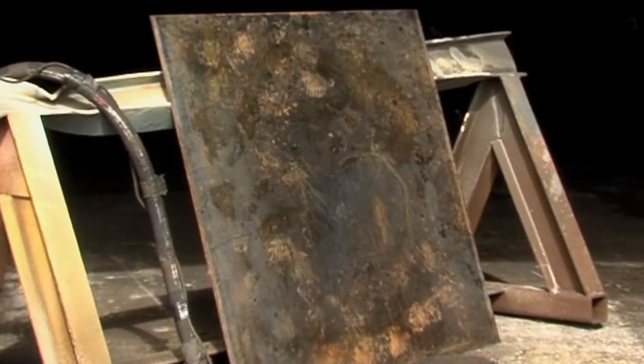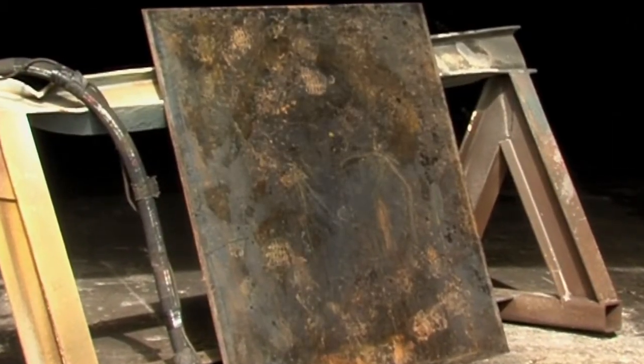The view under the microscope tells a completely different story, and we can prove it. Look at this piece of steel which was contaminated with sulfides and ferric chlorides and then cleaned to white metal. Within hours, the substrate has rusted. One side of the rusted area was treated with BMT and was analyzed within 4 hours. Energy dispersive X-ray spectroscopy reports showed no contaminants on the BMT-treated side.